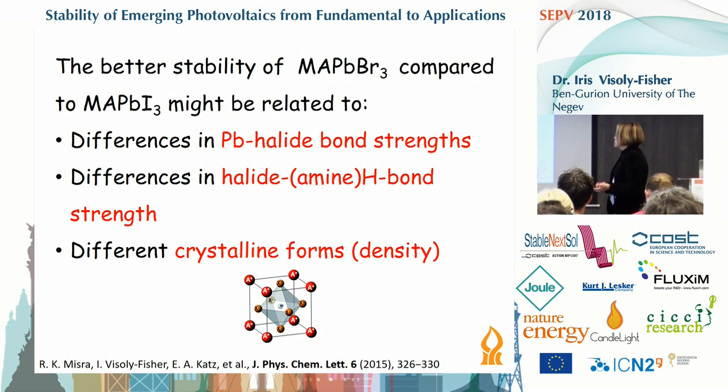It has stronger hydrogen bonds with the amine, and the crystal with the bromine is a bit more dense because it's a cubic structure rather than tetragonal in the iodine case. And so it would all make sense that it would be more photostable. So this was completed in a rather short time, and from that point on, we said, okay, why don't we